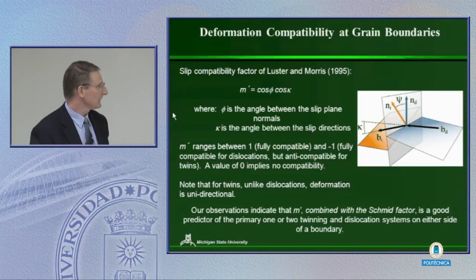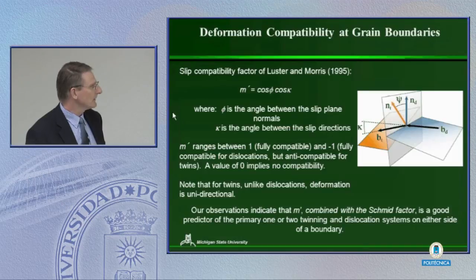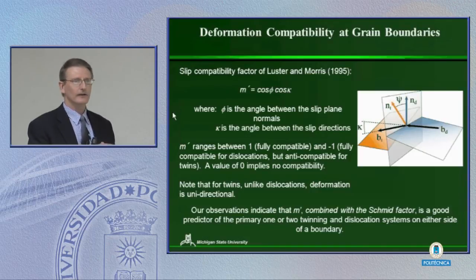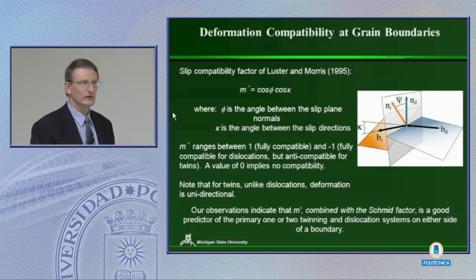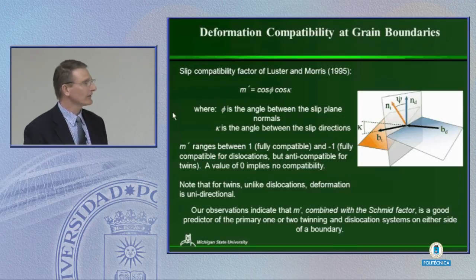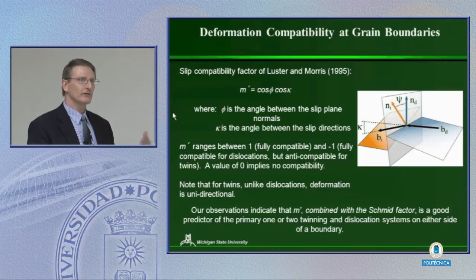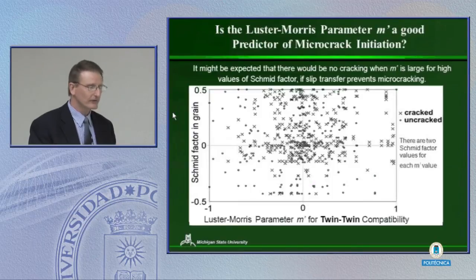Okay? And so if we look at this in detail, we find that in general, if we have a high M prime, we tend to see that's where we get evidence of transfer across boundaries. You maybe see a twin coming to a boundary and a dislocation pile-up moving across, or a twin coming in and a twin propagating across. And so the factor works really quite well in terms of deformation transfer. The question is, if you get deformation transfer, do you get fracture or do you not get fracture? It's a little bit different question.